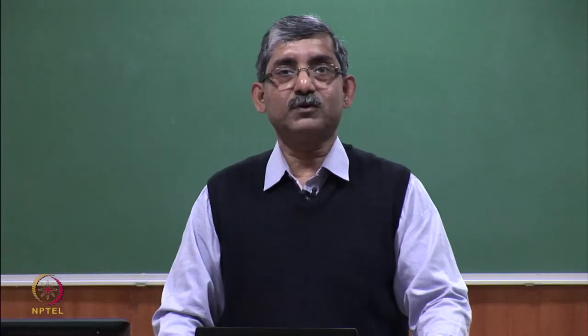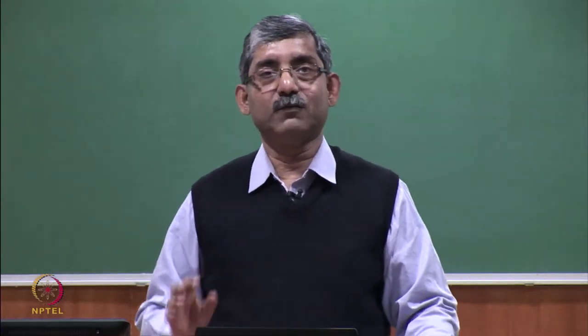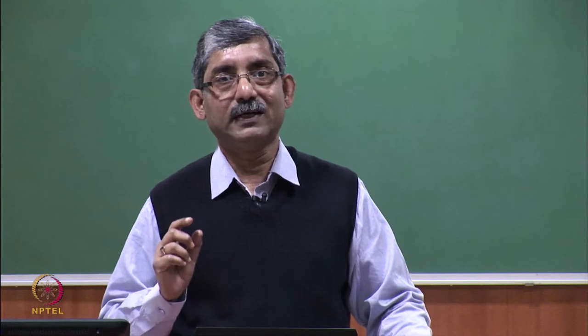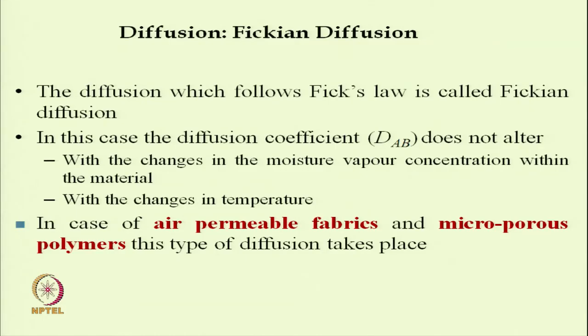So, the Fickian diffusion means here the diffusion takes place through the air pockets, and this type of diffusion is called Fickian diffusion. So, in this case the diffusion coefficient DAB does not alter with the change in moisture vapor concentration within the material or with the change in the temperature. So, diffusion coefficient is a constant parameter. So, in case of air permeable fabric and micro porous polymer, this type of diffusion takes place.